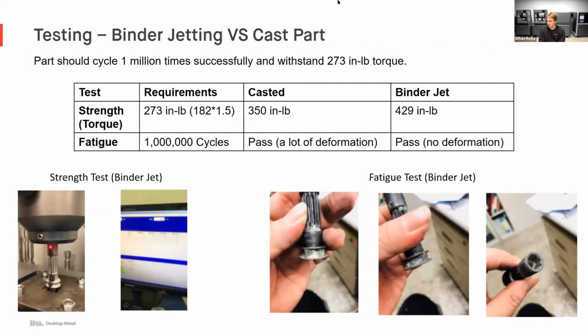After looking at the testing results, you can see that the cast part was able to withstand 350 inch-pounds and the binder jet part was able to withstand 429 inch-pounds. So it really exceeded the properties of what the cast alternative was able to do. When it came to fatigue and cycling, the cast part was able to withstand the million cycles, but it had lots of deformation after the process was complete. The binder jet part passed with very little to no deformation, so it could have withstood far more cycles than 1 million.